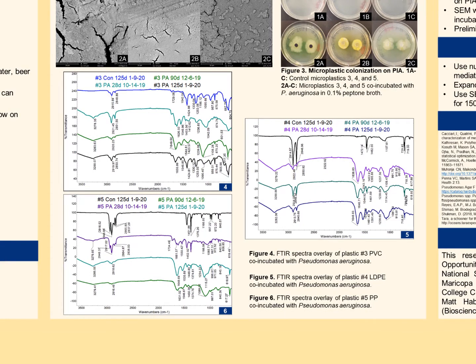Figures 4, 5, and 6 show our FTIR spectral overlay of our plastics PVC, LDPE, and PP. We can clearly see changes from the first timeline of 28 days to our final timeline of 125. Many of the characteristic peaks lower in intensity over time, while we get newer peaks increasing in intensity. These changes compared to our control confirm that the colonization of our Pseudomonas aeruginosa is having an effect on the surface of the plastic.